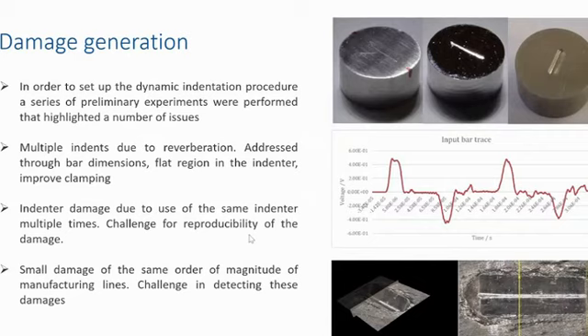And then another issue was related with the integrity of the indenter, because we wanted the indenter to be clear when there was some fracture or damage, in order to have, again, high repeatability of our damages. We initially used some hard magnetic steel that was having some plastic deformation and small damages, and then we passed to tungsten carbide, which is brittle, and when it fractures, it fractures.